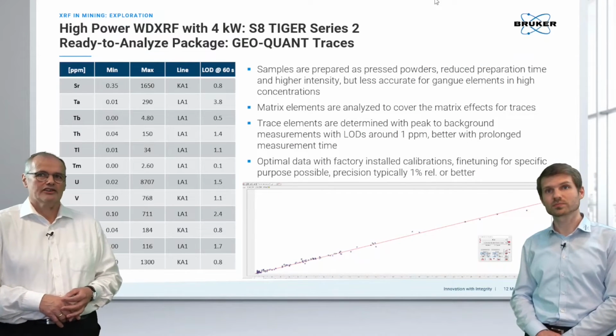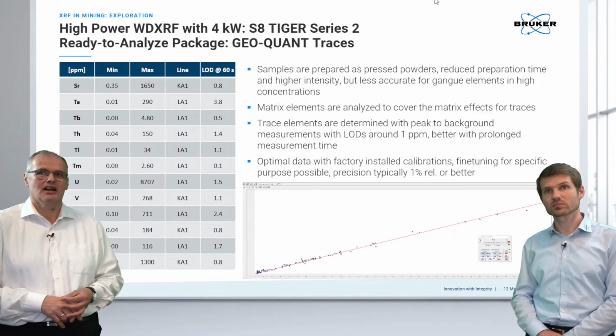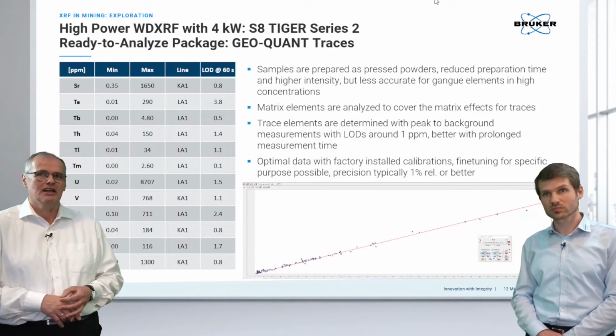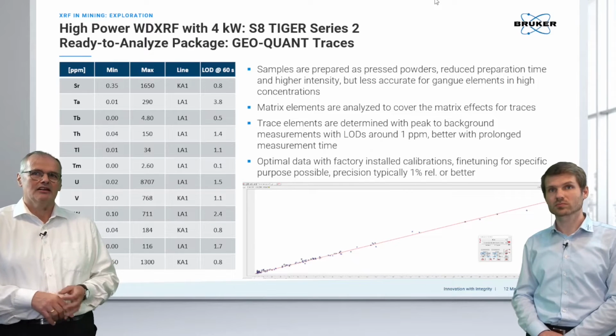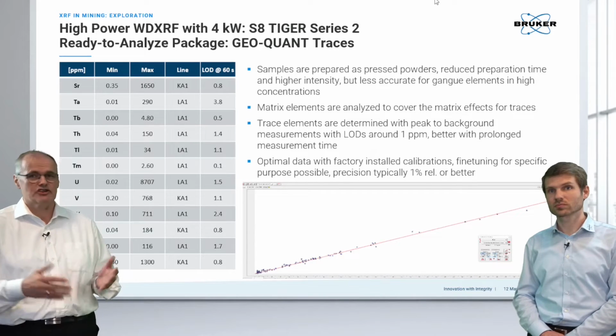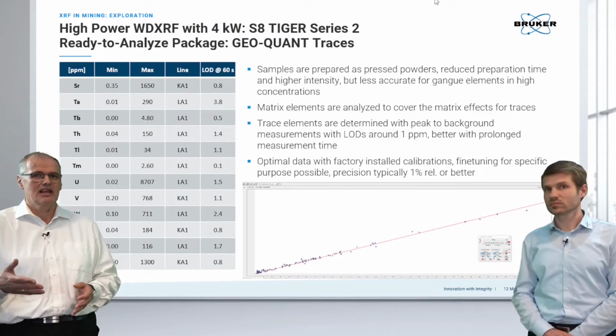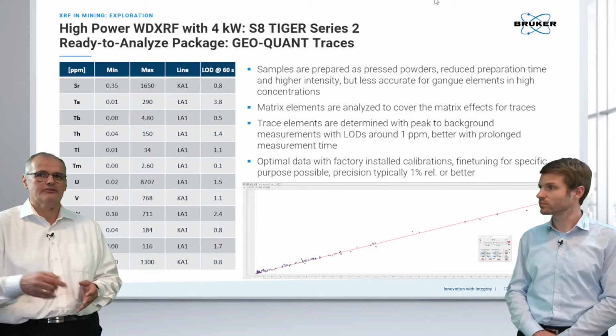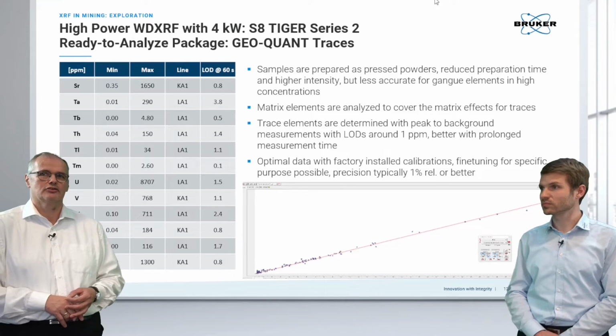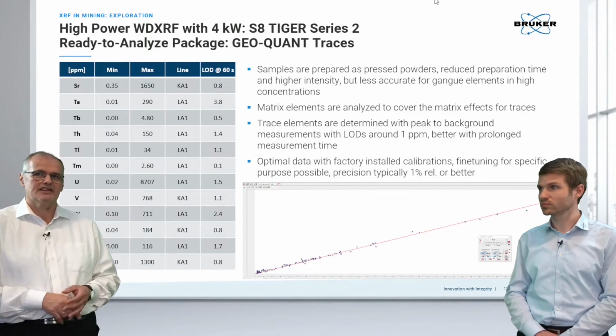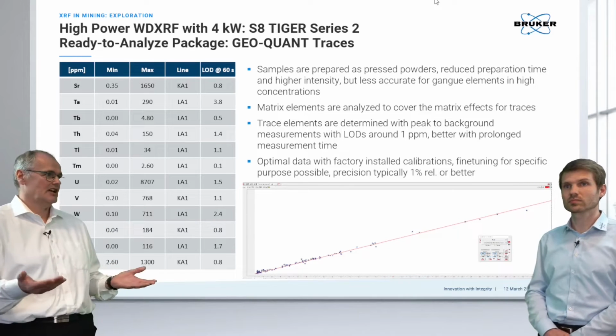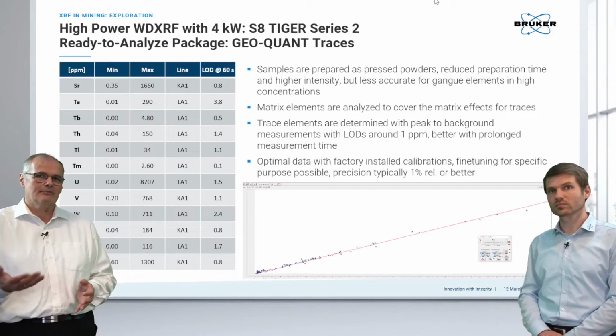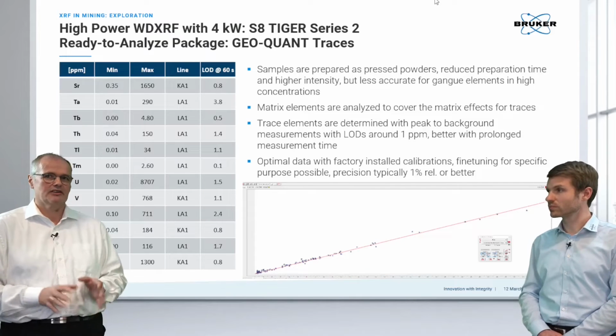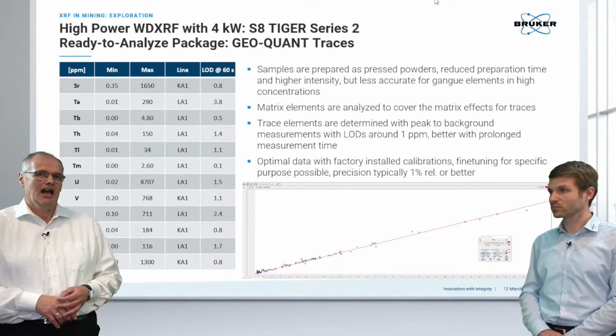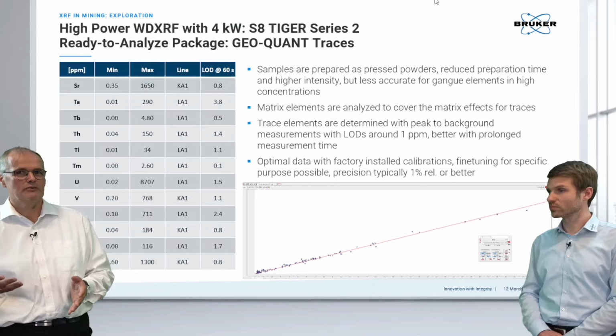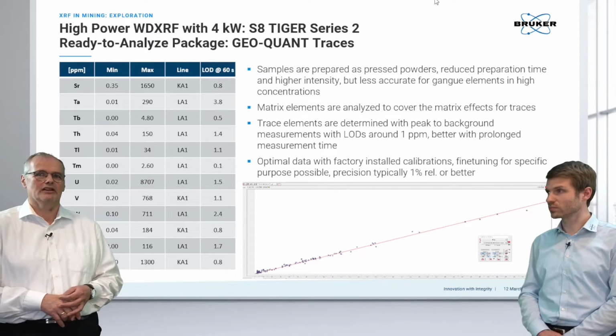Yeah. So actually, samples are prepared as pressed powders. This reduces the preparation time. It gives higher intensity. On the other hand, also the matrix elements, which might not be so interesting, are analyzed and taken into account to have a matrix correction giving a higher accuracy. And of course, we have set up the measurement method in a way that the typical LOD is about 1 ppm. This can be improved by prolonging the measurement time per element if I look towards a specific element. And sometimes we can even achieve sub-ppm in a pretty good way.